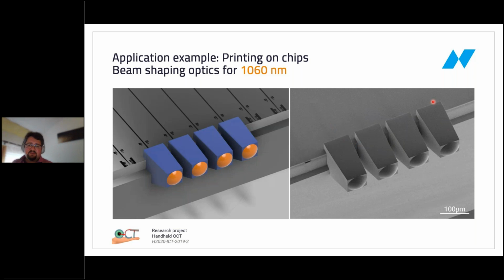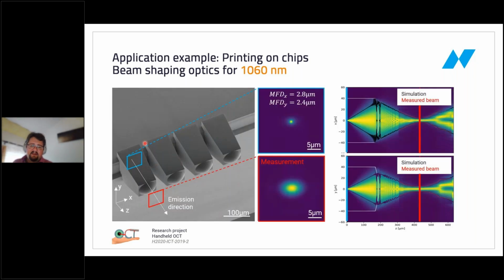And we characterized this as well. So here you can see the lenses again. The blue part here shows this region. We just did a simulation because we couldn't measure, obviously, the light inside the polymer. The light here starts as a very small mode confined to the waveguide, and then the beam is allowed to expand in the lens. As soon as it's outside of the lens, we can measure the beam shape and intensity distribution. As you can see over here, where we overlay the simulation and the actual measurement, we are in very close agreement. So we managed to design the proper beam shape that we wanted to have, for example, in this case, collimating the beam to a specific diameter, and the beam shape and the direction match perfectly for all these lenses.